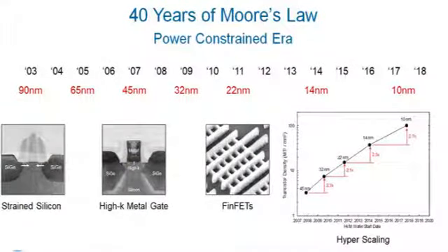That's right. But when you look under the hood, your first big invention was strained silicon, right? Yeah, so at that 90 nanometer generation in 2003, we realized we couldn't keep scaling the traditional transistor structure that used silicon dioxide and then polysilicon without incurring much higher, intolerable leakage levels. So we came up with strained silicon, a way of staying with those known materials in the gate electrode, but still enabling improved transistor performance without incurring a higher leakage power. So that was the first of some important innovations needed in that power-constrained era.